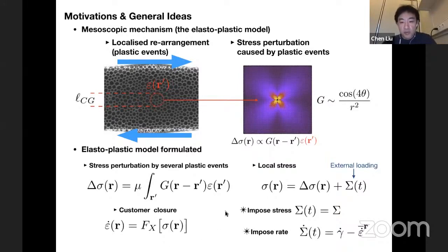So with this framework, how to implement different driving protocols? To impose stress, you just set the external loading to the stress you want. If you want to impose a constant shear rate, you add an extra dynamics on the macroscopic stress, which works like a feedback loop that you apply the stress in such a way that the macroscopic shear rate is a constant.